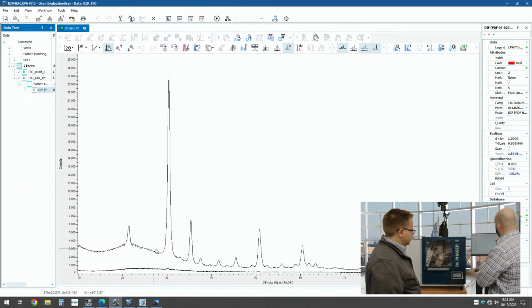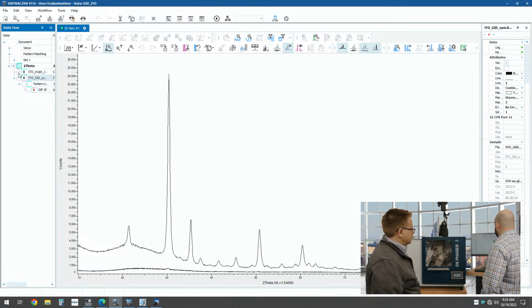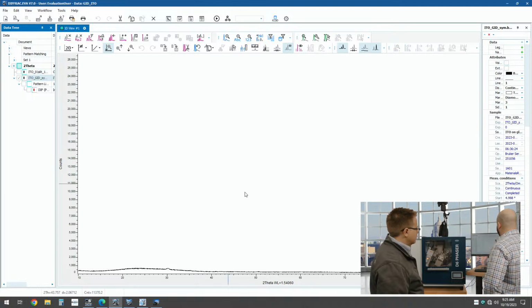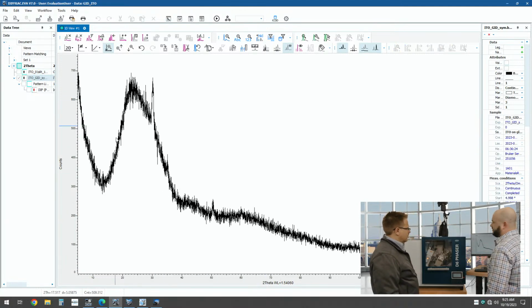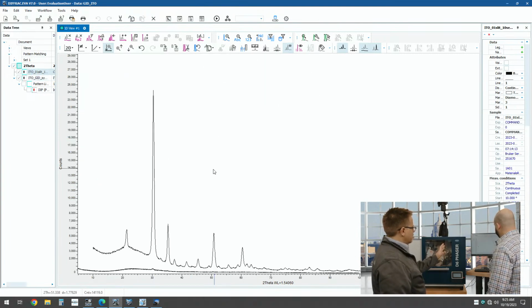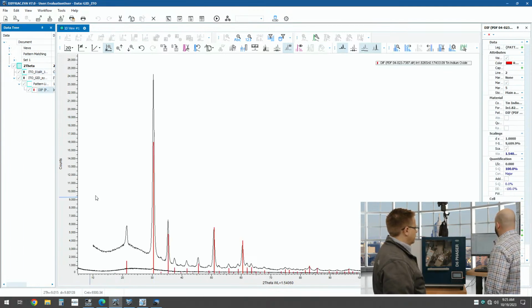So you can see on the top here, if we turn to the computer, I have our grazing incidence measurement where you see all these crystalline peaks come out from that film, that 25 nanometer film on the surface. If we remove that and just look at what a coupled scan would look like, you'd see this amorphous component. You don't really see any crystalline peaks. You get some indication that there are some peaks there, but it's mostly just the glass. Right, exactly. And so then we can do a little phase ID, and you can see this is indium tin oxide.